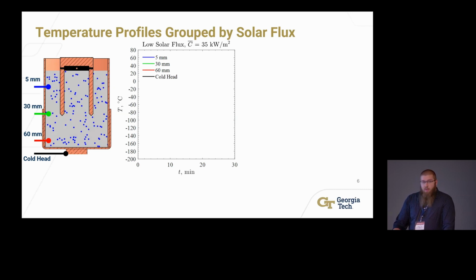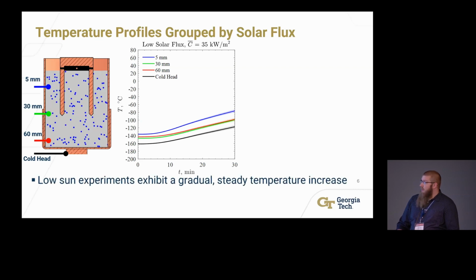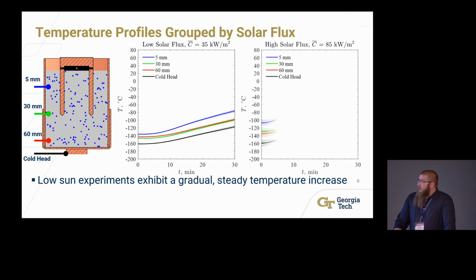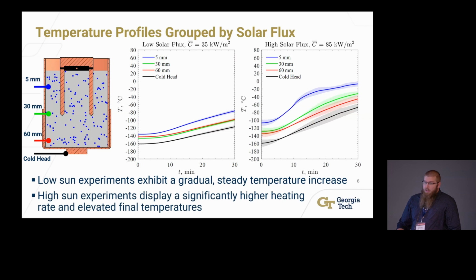The packed bed is allowed to cool down to a set point temperature and pressure before the experiment begins, which is at 0 minutes, where we start the solar simulator and allow the experiment to run for 30 minutes. And here we can see the low sun experiments, which show a steady and gradual temperature increase over that 30-minute time period. And then moving on to the high sun experiments, we can see the much higher heating rates, as well as higher final temperatures.